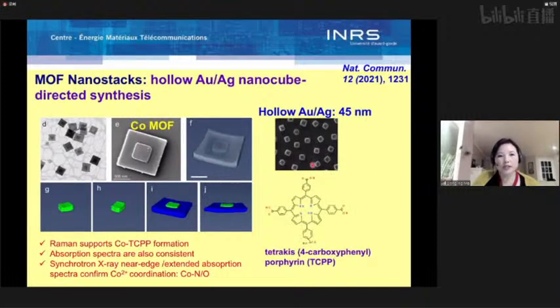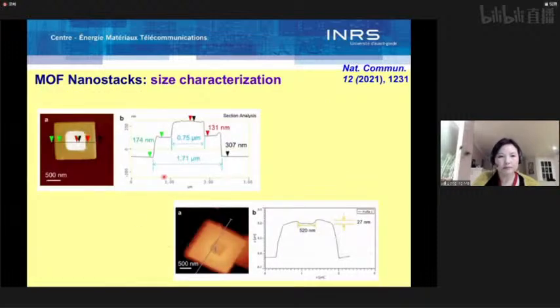About the synthesis first, we use hollow gold-silver nanocubes as inducers to induce the interaction between cobalt precursors and the TCPP to get a cobalt MOF structure. A small plate was formed first, which further induced the synthesis of the large plate, giving nanostacks composed of a smaller nanoplate of cobalt MOF and a larger cobalt MOF. We used synchrotron techniques and other techniques to confirm the formation of cobalt coordination with nitrogen or with oxygen.